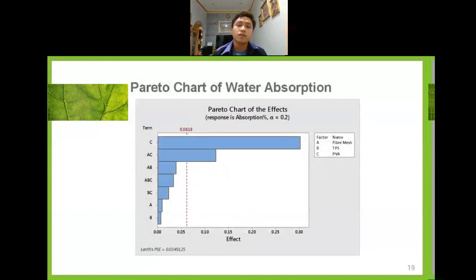The next slide is the Pareto chart for the water absorption. From the Pareto chart of water absorption, it can be concluded that the thermoplastic combination from cassava starch and glycerol cannot protect the fiber from absorbing water, because the cohesion of the matrix and reinforcement can be damaged even in bulk by moisture or chemical surface attack.